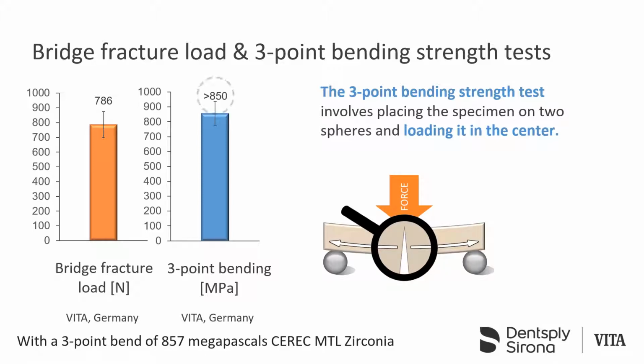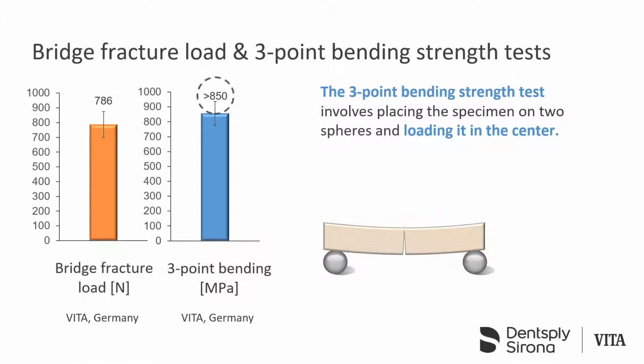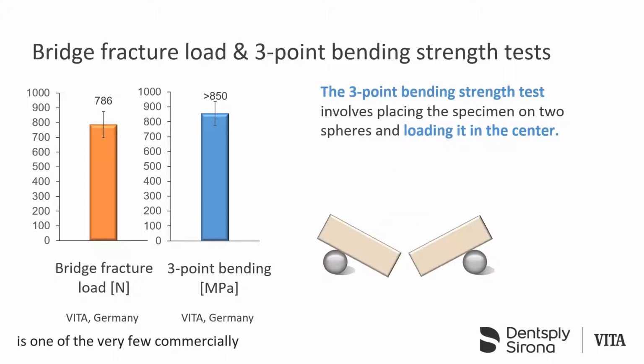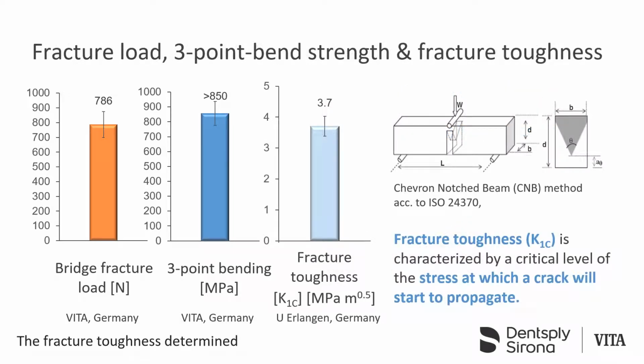With a 3-point bend of 857 megapascals, CEREC MTL Zirconia is one of the very few commercially available 4Y-TZP dental chairside ceramics that exceeds the requirement of ISO 6872, which is 800 megapascals. The fracture toughness determined using the CNB method, according to ISO standard 24370, is 3.7 megapascals times the square root of a meter. The authors of the study conclude that CEREC MTL Zirconia performed significantly better than Katana STML.